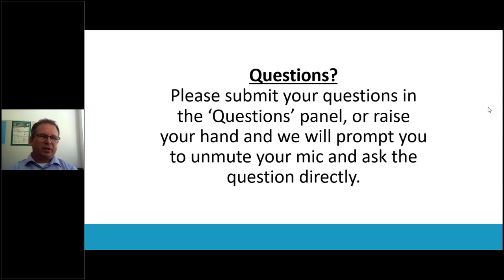Thank you very much for the interesting question. Now I have to split the answer into two parts. One is the DVS measurement. For the DVS measurement, we are really taking care to reach an equilibrium value. That means there should not be any gradients anymore, and especially for the thin material, around 10 micrometers, it's not the exact value, but we can be quite sure that the distribution will be uniform and really representative for the bulk material.